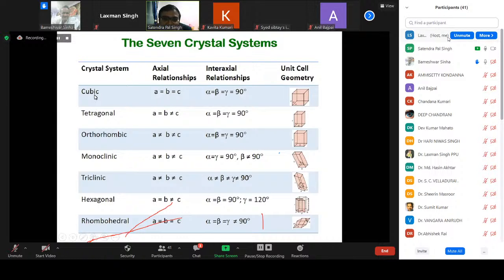We have the cubic crystal system. What is special about this? The axial relationship is a = b = c, and the interaxial angles alpha, beta, gamma are all 90 degrees. This is the most symmetric in crystallography. The tetragonal is one where the c axis is not equal to the other axes. a and b are equal, but the angles are always 90 degrees. So the tetragonal looks something like this. The third one is orthorhombic. In this, all the axes are unequal, but the angles are always 90 degrees. So it looks something like that. Then comes the monoclinic system. Here, all the axes are different, but alpha and gamma are 90 degrees, and beta is not 90 degrees.